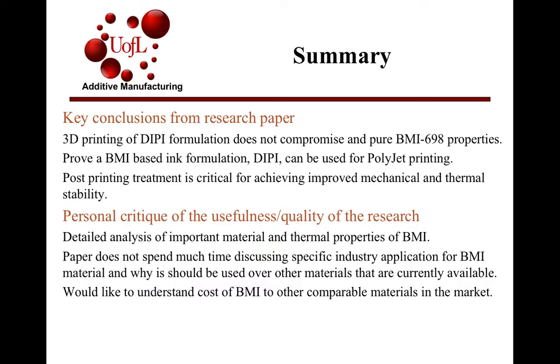So some key conclusions from this paper are: 3D printing of the DIPI formulation does not compromise any of the pure BMI-698 properties. Secondly, they were able to prove that a BMI-based ink formulation, here they call it DIPI, can be used for PolyJet printing, which is the first time that this has been done in the industry. And then lastly, they were able to prove that post-printing treatment is critical for achieving good mechanical and thermal stability of the material.